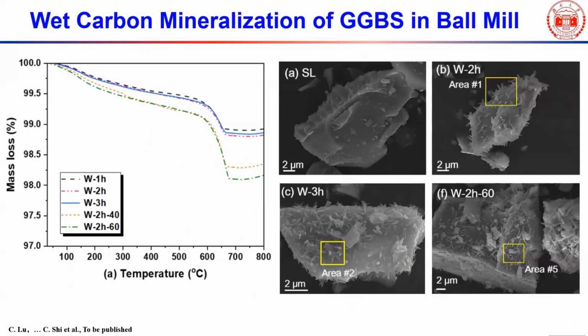Actually, my students also did quite a bit of work on this topic. We tried initially to carbonate blast furnace slag in a ball mill. We used a wet ball mill for 1 hour, 2 hours, 3 hours, and also at 40 and 60 degrees C. You can see the weight loss, or the calcium carbonate formed, is only 1 to 2%, right?